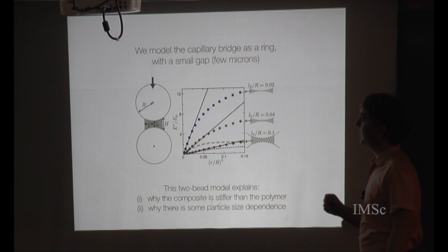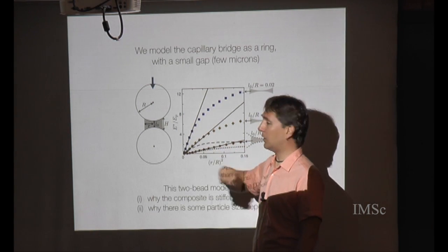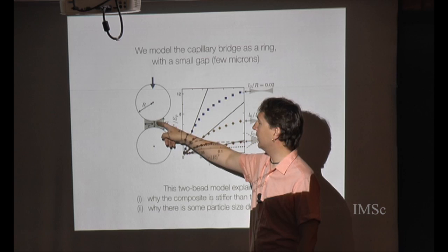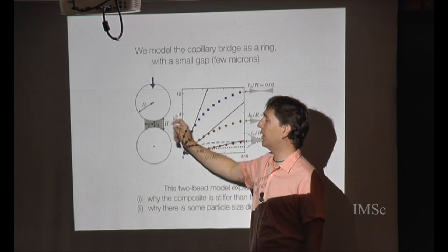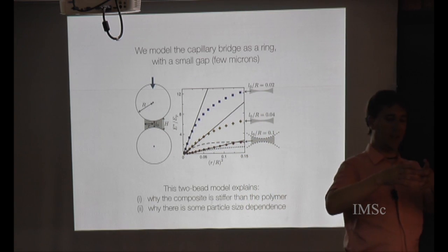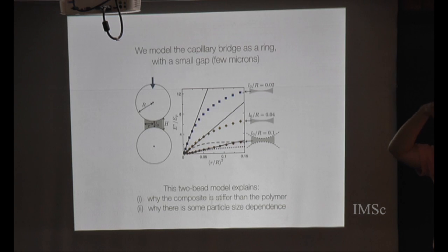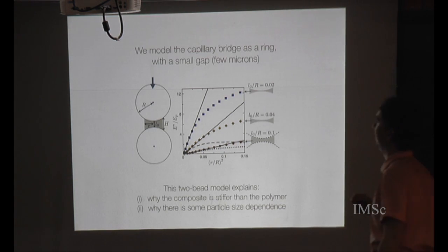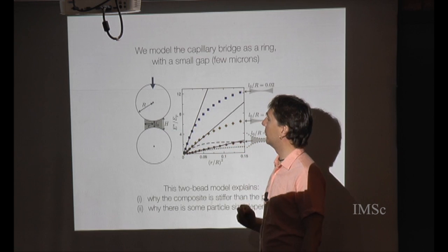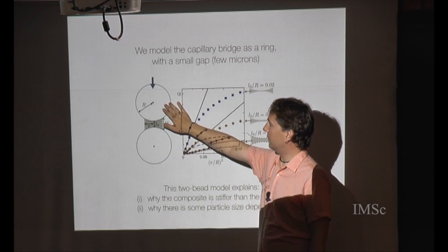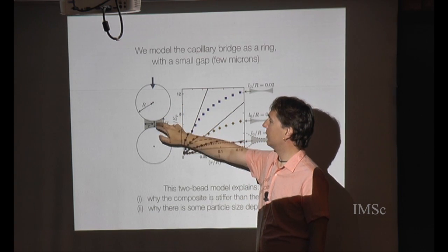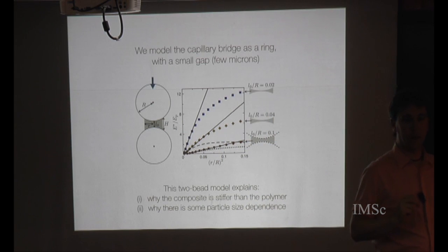So what we can do is take 2 spheres and model them with COMSOL, and fill the gap between them. It's a cylinder truncated by the spherical caps, if you want a specific definition, filled with a polymer. If these are assumed to be rigid, you can then look at the elasticity of the polymer.